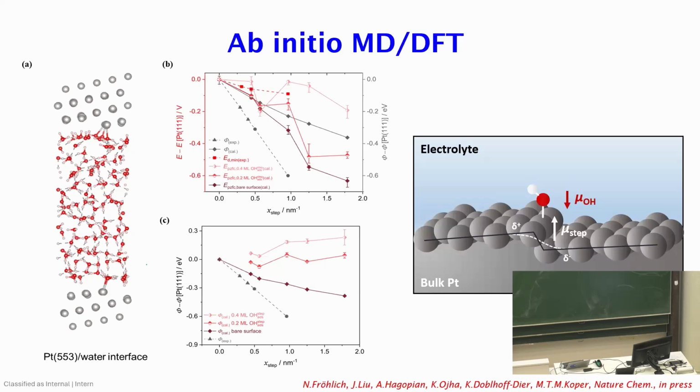So in my mind, this is another piece of evidence that we have adsorbates sitting in the step site where we measure the potential of zero charge. We have adsorbates sitting in the step site, and they quench the dipole, the electrostatic dipole of the step site.